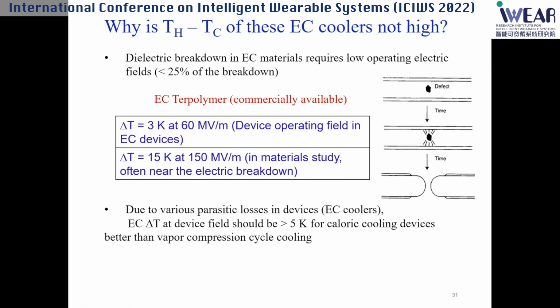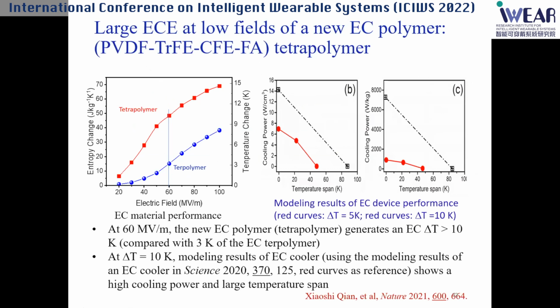So the question is, can we get a larger electrocaloric effect? I don't have time to go into a lot of details, but basically here's another case - we expanded from PVDF-TrFE polymer to a new polymer. We can generate cooling that goes from 3 Kelvin at 60 megavolts per meter to more than 10 Kelvin. Very simple, right?